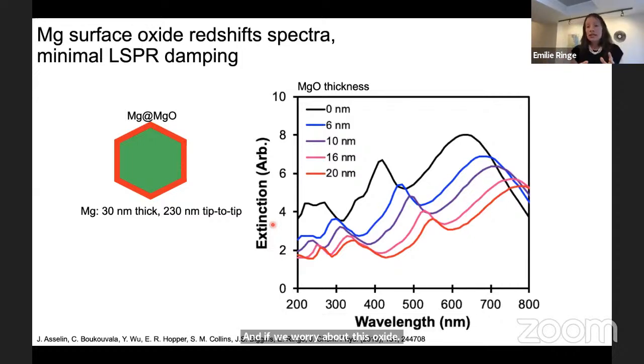If we worry about this oxide, we can ask ourselves, how does it change the plasmonic properties of the structure? Unfortunately, we can't really ask that experimentally, since we haven't been able to control that oxide thickness yet. But we can ask numerically, using discrete dipole approximation solving of Maxwell's equations. What you're seeing is a pretty large particle, typical size that we make, with plasmon resonance in the visible, and an increasing thickness of oxide layer without changing the thickness of the magnesium nanoparticle. All you see here is really just a redshift. So we're pretty content that this oxide layer isn't damping the plasmon resonance, and that it's probably not making a large dent in our possibilities of applications.